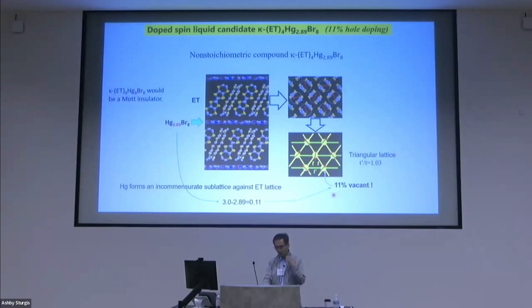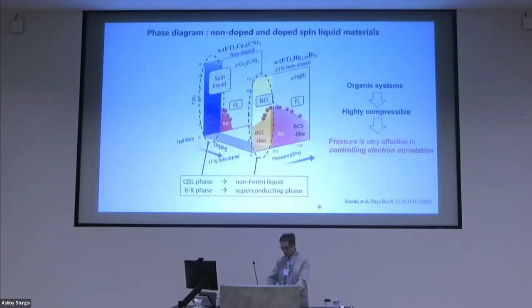And the correlation, the on-site Coulomb interaction U, can be roughly estimated by molecular orbital calculation. This U is predicted to be much larger than the previous one. So this is the doped molecular Mott insulator with a triangular lattice. Okay, an 11% hole-doped Mott insulator with a triangular lattice.